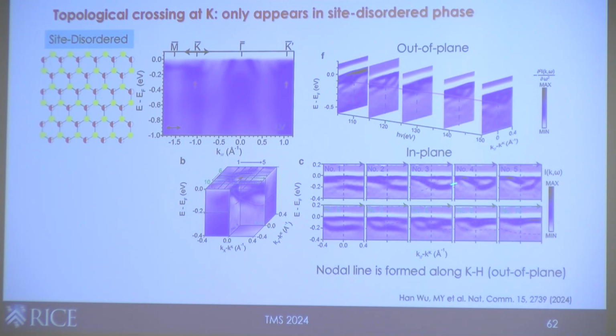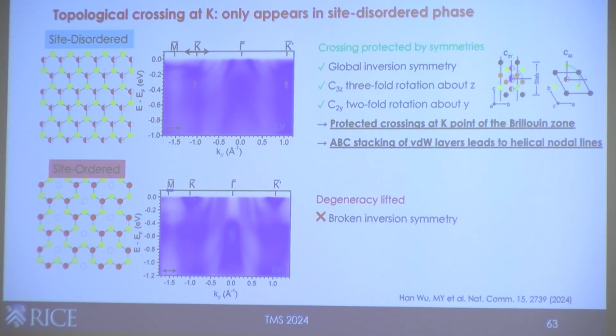You see that it's basically a bunch of cuts. You can show this is where the Dirac point is. If you go left, right, up, and down, there's a gap that opens. So this just looks like a Dirac crossing. It's interesting to think about because even though locally it breaks inversion, the global inversion symmetry is protected, and it also has the C3z symmetry and also C2y. These together would give you the crossing at the K point.